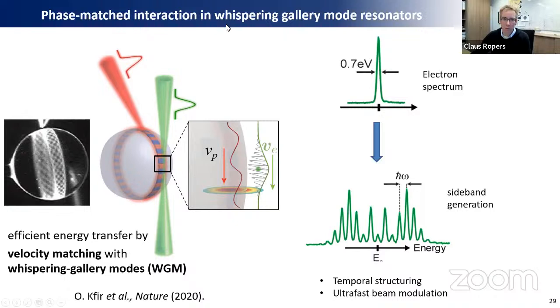Yeah, so what we've looked at are these whispering gallery mode resonators. They are dielectric spheres, very well known from, I guess, cavity quantum electrodynamics studies. They actually have the nice property that besides enhancing the optical field within these modes, you can actually make sure that there's phase matching in the interaction of the electrons with these optical modes as soon as the electron group velocity coincides with the optical mode's phase velocity. When that's the case, the electrons can basically interact with the same phase of the optical field for prolonged times and really produce quite strong interaction and really populate multiple of these sideband modes.